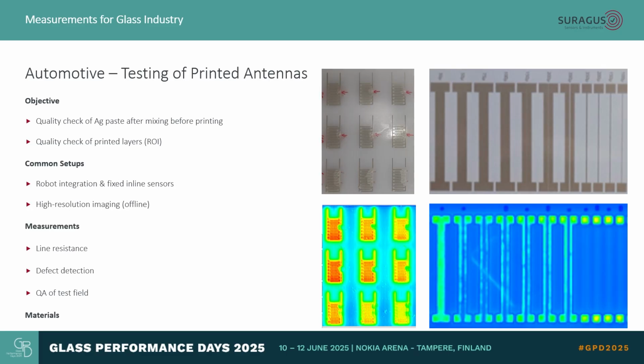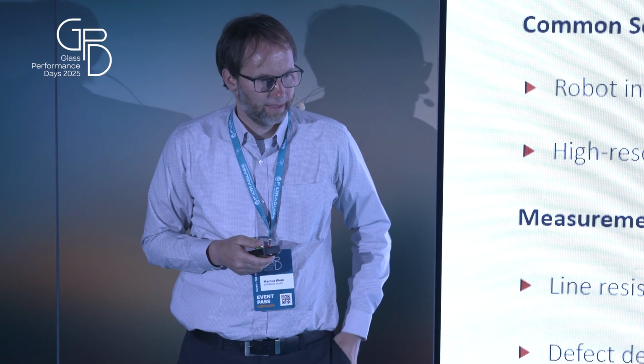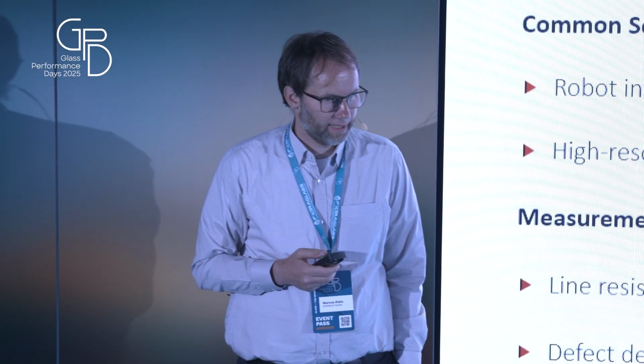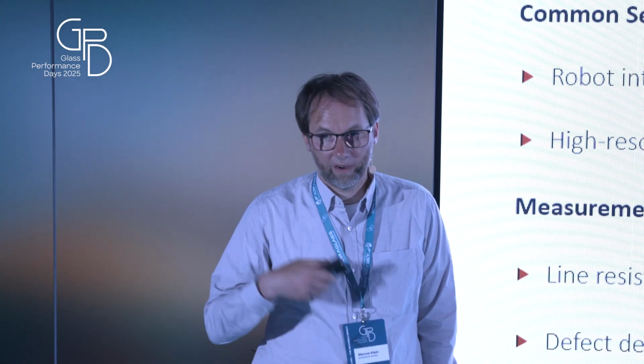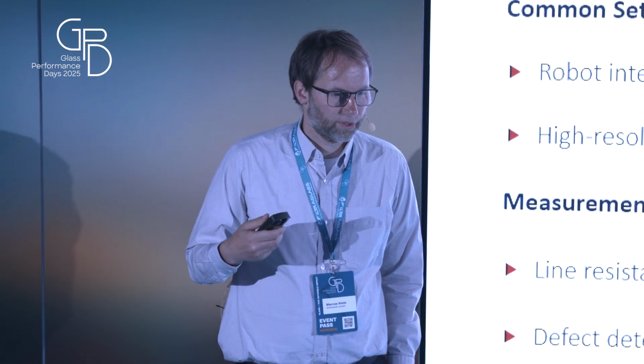Another topic is antennas in windshields. There are a lot of antennas these days. And of course, there needs to be the formulation of the paste. So we have a sensor which is analyzing the paste when it goes through a pipe and it interacts with electromagnetic fields. So we can see the paste composition, the dielectric and electric properties of this paste, and we can predict processability downstream. Later we can also test the printed antennas and see whether the line resistance is correct or whether there are defects. Very often the optical image does not tell the truth about the electrical performance.